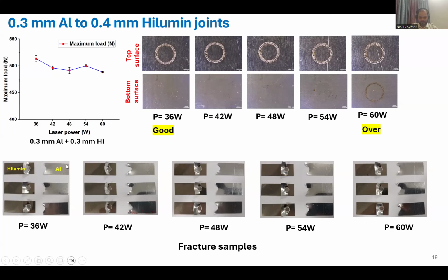Here, the same concept is used to capture the good weld and overweld. Here you can see there is hardly any penetration on the bottom sheet. There is no penetration, it seems quite good, seems quality, and we are breaking the top surface from here. So this is fulfilling the welding definition, and this is also fulfilling the battery criteria, bottom sheet not penetrated. So this can be used as a weld parameter for connecting the cell.